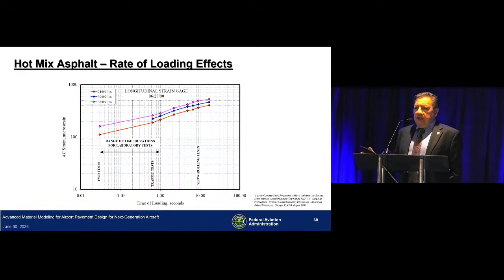If you look at the stiffness behavior of asphalt concrete, at low temperatures or very high rate of loading, very high frequencies, you see almost elastic behavior. Then you run into viscoelastic behavior. And then at very high temperatures or very slow rate of loading, you see viscous flow. This is a log-log curve, so keep that in mind. So when you're in slow rolling response tests, you're measuring viscous flow. When you're measuring responses under the falling weight deflectometer, you are measuring the elastic part of the curve. And this is where we were with the traffic test. So we still have a very significant effect of rate of loading. And these are at different loads, 24,000, 30,000, and 36,000 pound wheel loads.